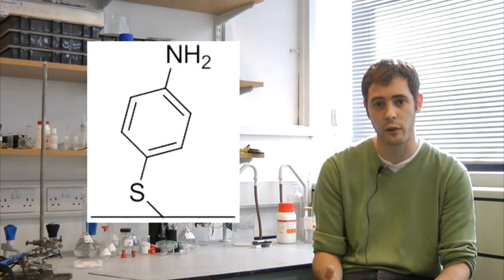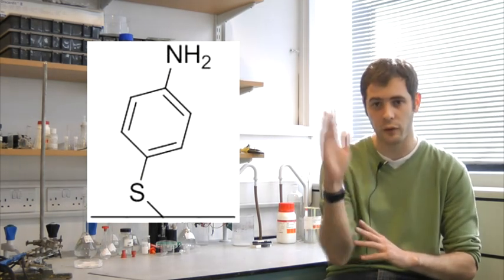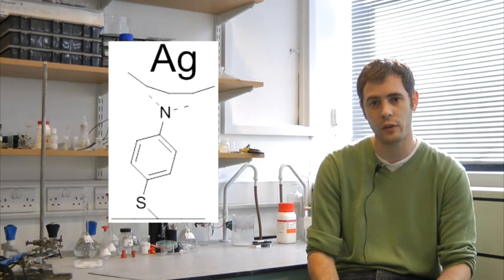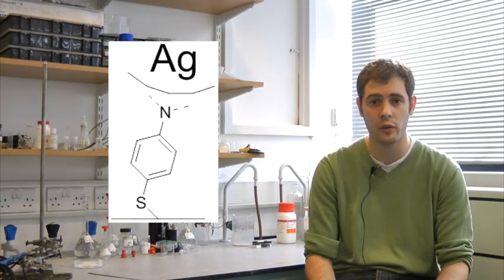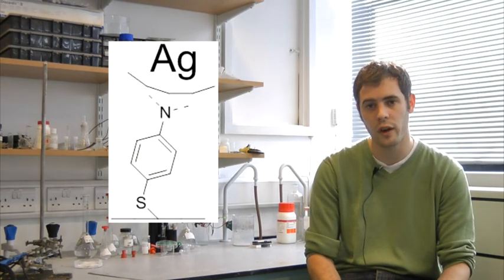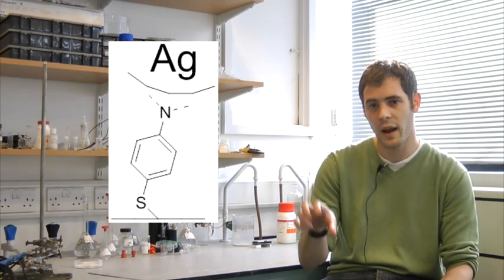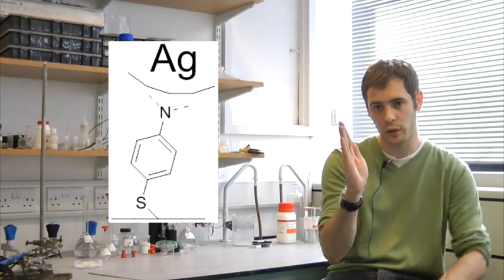One of the most successful parts of my PhD was using nanoparticles. So I took one of the SERS substrates and I added silver nanoparticles to the top, and I did that by forming a layer of mercaptoaniline, which has a sulfur at one end that binds to the gold very, very strongly, and a nitrogen at the other end that kind of sticks upright, almost like a forest of organic molecules. When you place that in a solution of silver colloids, or silver nanoparticles, the silver forms a strong bond to the nitrogen, and it sticks.